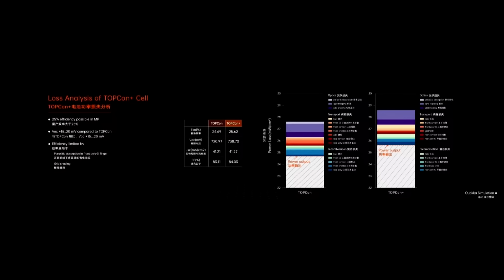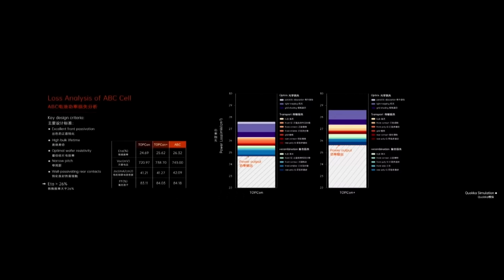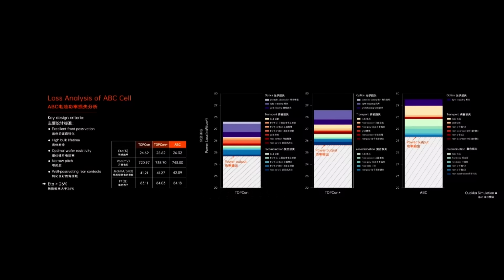So, and now the question is, of course, how can we get even better than this cell? And when we look into the loss analysis, we see that we are still limited by parasitic absorption, especially in the front polysilicon fingers, but also by metal grid shading. And that leads us to the all-back contact solar cell, which has been successfully developed and launched by AIKO. Here we achieve an even higher VOC and a remarkably high JSC of more than 42 milliamps per square centimeter, which gives us an efficiency of 26.3% and more. And with this, I would like to conclude.